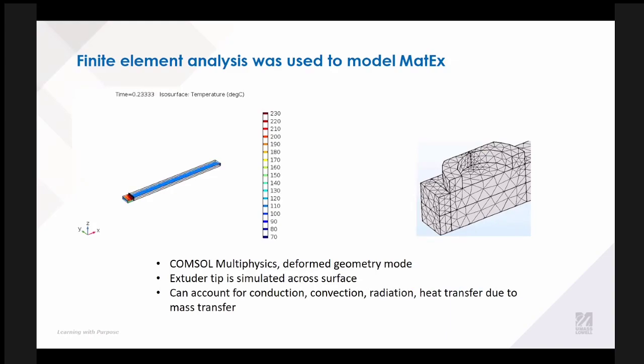So we have developed a finite element model that can simulate the printing of polymers in different geometries. What I'm showing here is an animation of a single road width line. It's the same geometry as the work from Seppala and Migler, but we've squished it so that there's a little bit more resolution in the Y dimension. And what we end up seeing is that there isn't a ton of variation across the width of the bead, but we do see very, very rapid cooling occurring as the material is being extruded.